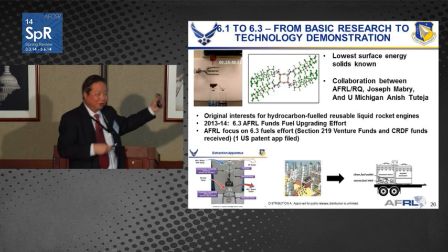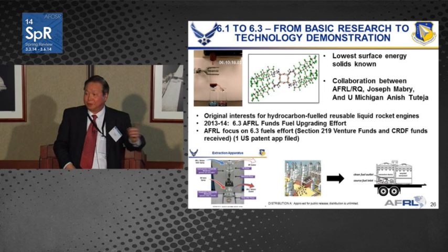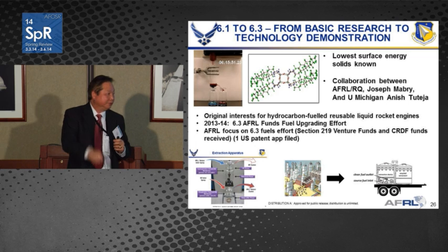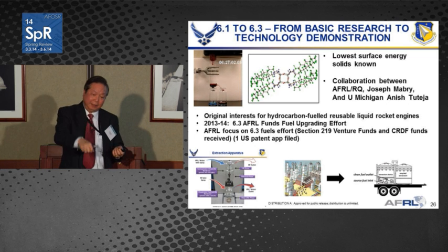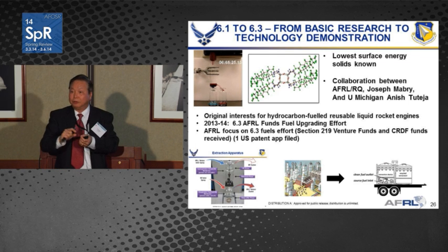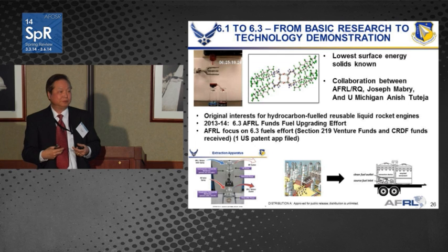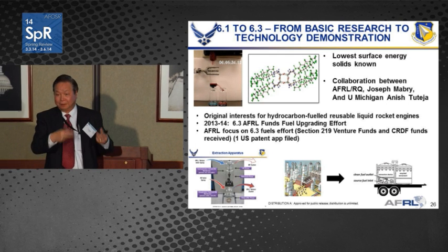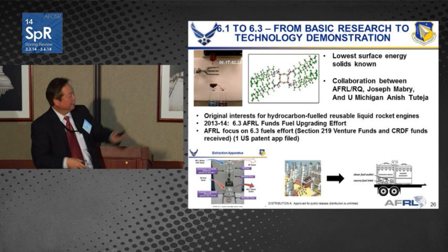2 minutes, so I can talk a little bit more. This is also solution processable. Therefore, you could dip coat any surface and get the properties that you want. So they could apply it to a wire gauze and coat all the wire to have these properties, but also leave gaps for the liquid to go through. You could do it with fabric to allow the liquid to go through, but give you the surface properties that you want. It would be difficult with some of the phobic surface approaches because they all use a solid substrate in order to build a surface.